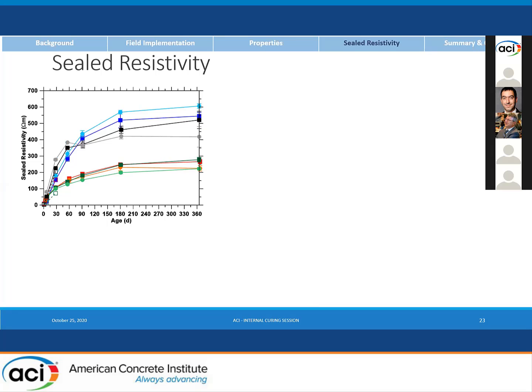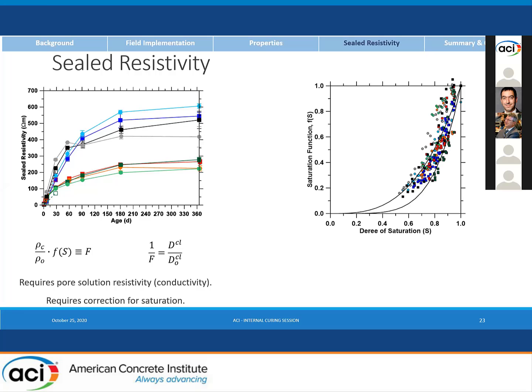You'll see that those lines are nowhere near one another, and it's because there's a couple corrections that need to be applied. So there's the pore solution resistivity, which I won't talk about here. I will just recommend that it be calculated for the moment. And then there is a correction for the saturation function. So we went ahead and we measured this for all of the different specimens. We chopped the cylinders into 3 pieces, measured all 3 pieces.